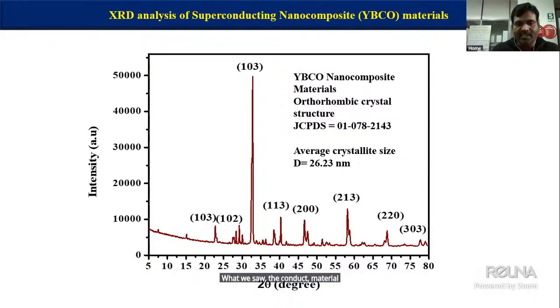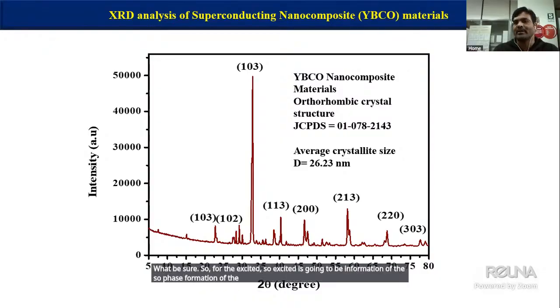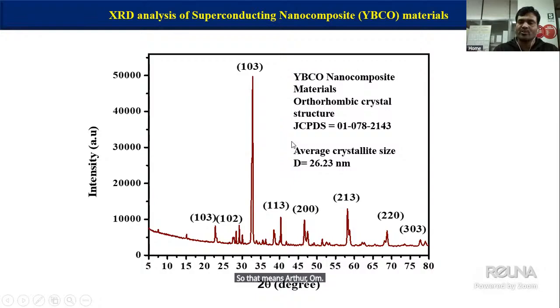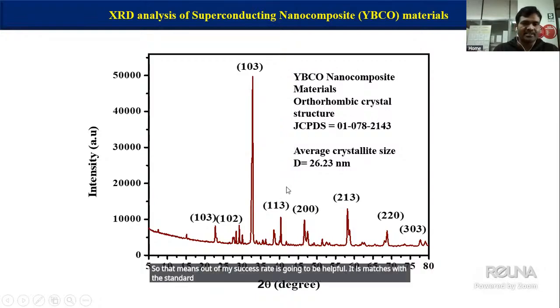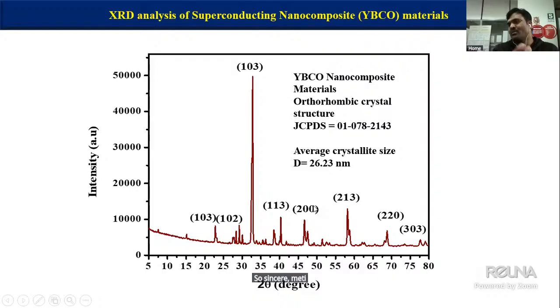So for the XRD analysis, it gives information on the phase formation and the crystalline nature of the material. We can see the higher intensity of the peak, which indicates superconducting material. That means an orthorhombic crystal structure is present, and it matches with the standard JCPDS number. Average crystalline size was calculated by the Debye equation, around 26 nanometers. So the synthesized material is confirmed as YBCO superconducting material by XRD analysis.